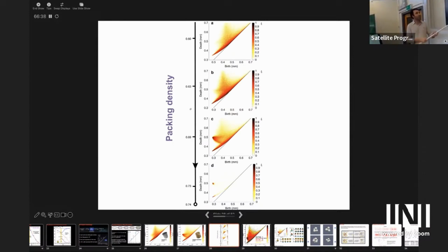If a point is here, it belongs to an octahedron. If it's further away, based on this Gaussian distribution, you give it a different amount of weight, and you can identify how many tetrahedra, octahedra, FCC, or HCP you have in the system. That's how you can robustly measure, and you then compare this with the other. You can create full-crystal FCC or HCP and compare it to these experimental patterns. Fine, that's good.